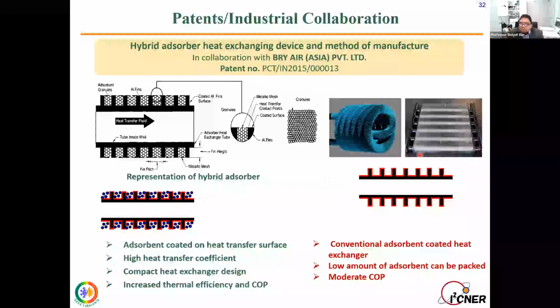Another thing is we made an advanced hybrid heat exchanger. Usually people use only loose grains in the bed, but we are using some binding materials. We call it a hybrid heat exchanging device. The adsorbent is coated in the initial phase, and then we also have the loose grains here, so that we have more adsorbent material. It improves the heat transfer performance and also has more metal, so that we can get more efficiency. It can increase the compactness of the heat exchanger, increase the thermal efficiency, and also the COP values of our heat exchanger. This is some of our patent work with industry.